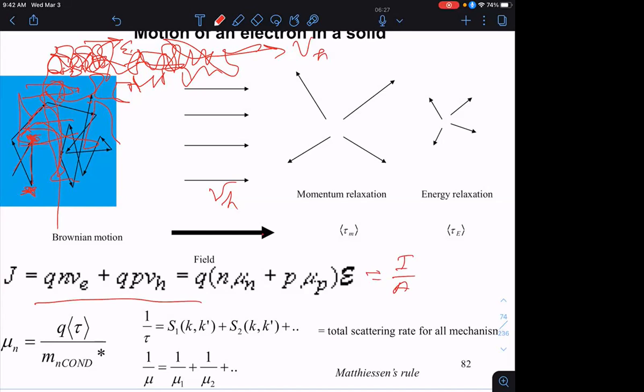Okay. Now this expression for the mobility, I'm not going to derive this, but I'll make this hopefully physically meaningful. I'm looking at the electron mobility, same thing for the hole mobility. It is given by the charge of the electron times the average time between collisions. Remember we said it collides with defects? Well, there's some average time between scattering events or collisions, which I call tau, divided by effective mass, but this is the conductivity effective mass. So this is the third effective mass that I told you last time we'll be talking about.